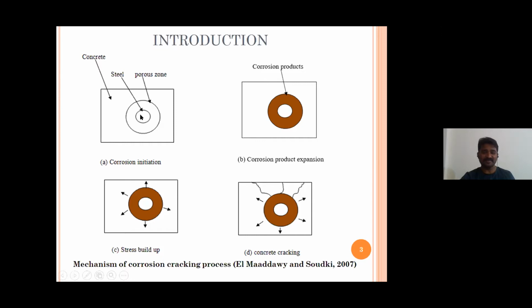Okay, so this is my steel. Assume that this is 10 mm, and I've just made it a little larger so that we can understand what the porous zone is and what its importance is. See, once corrosion initiates in steel, it does not induce expansive pressure straight away. It takes a lot of time. Why does it take a lot of time? Because those corrosion products must fill the porous zone thickness first. Then only can they exert expansive pressure.